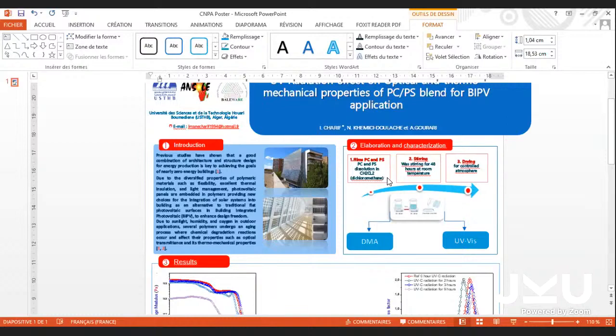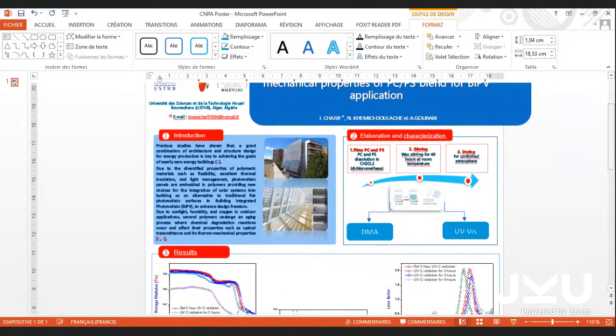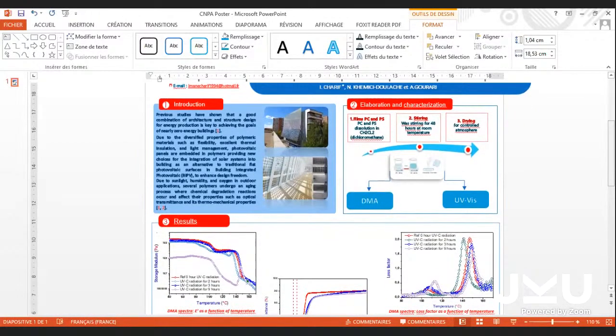So, in this study, we used two polymers, polycarbonate and polystyrene, and to prepare them, we used the solution casting method, where we dissolved them separately using dichloromethane solvent, and they were stirred together and then dried. The films were then exposed to UVC radiation for 3 different intervals of 3, 6 and 9 hours, to detect their UV stability.